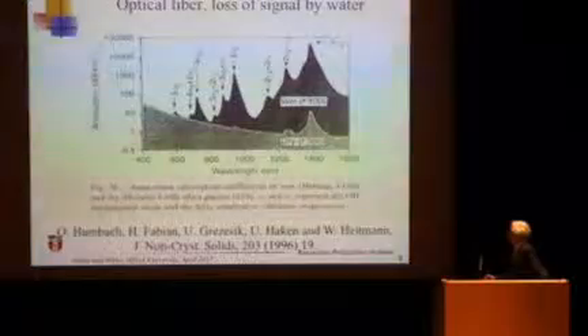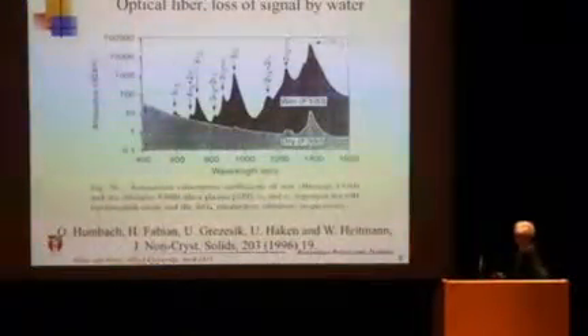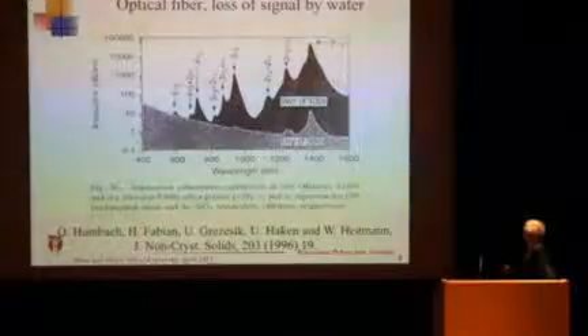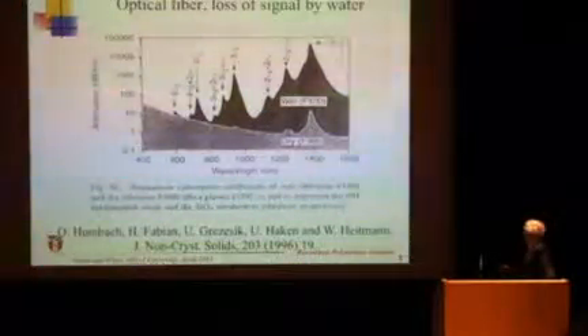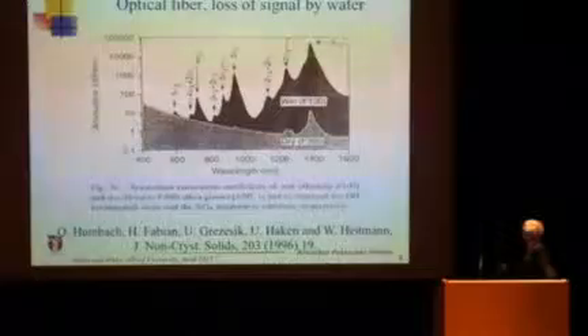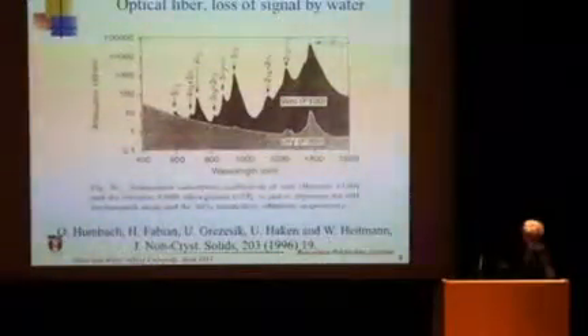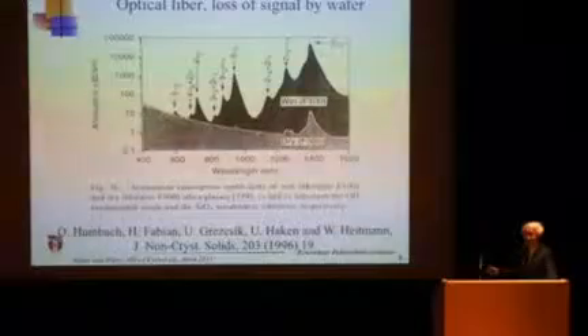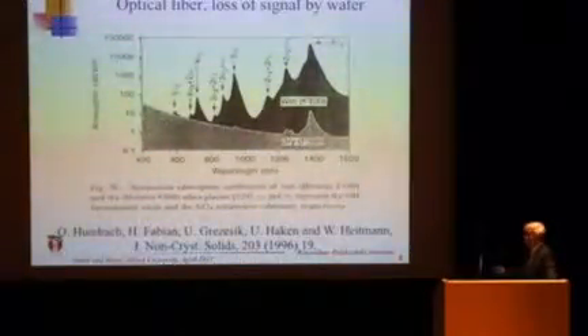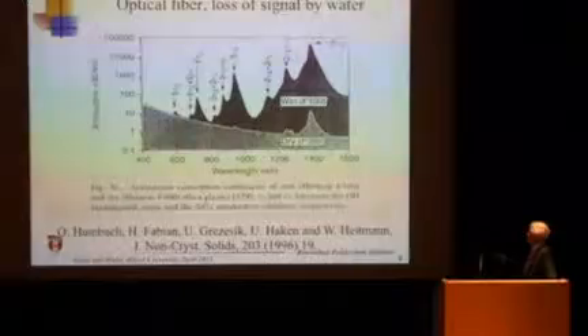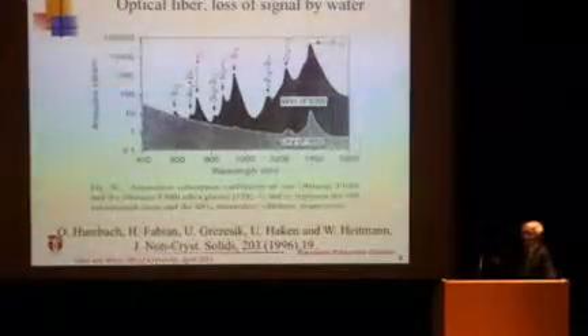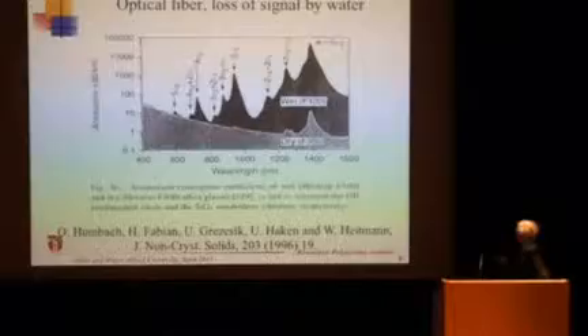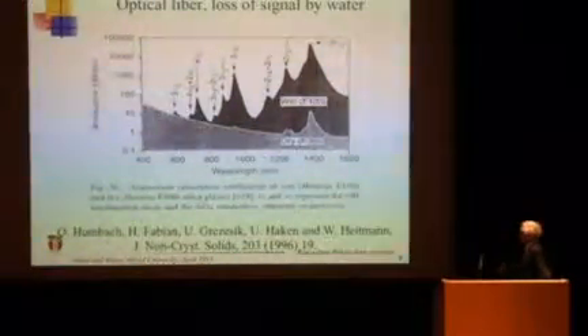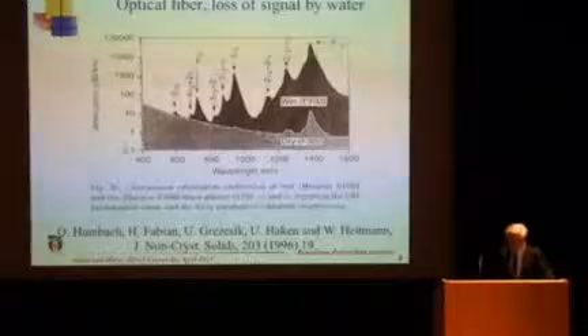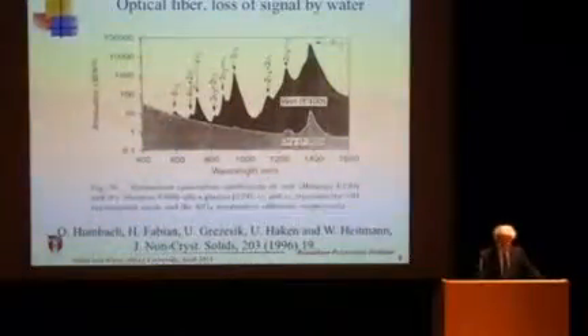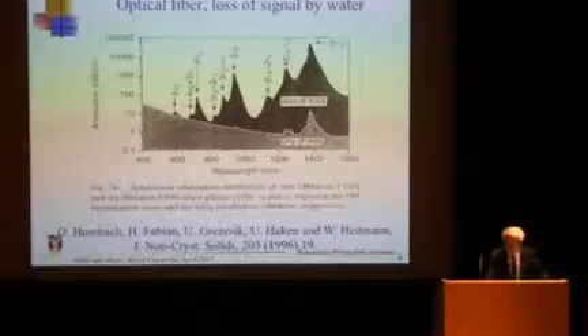This is a well-known optical attenuation curve by German scientists. This is the range where our telephone communication is used, here or here, 1300 or 1500, and there is large absorption due to water. If a trace amount of water is included in optical fibers, you have large loss. An optical fiber made of this glass would not be useful. If you make it in a very carefully dry condition, you still have this water band. So optical fiber development was a battle against water impurity.